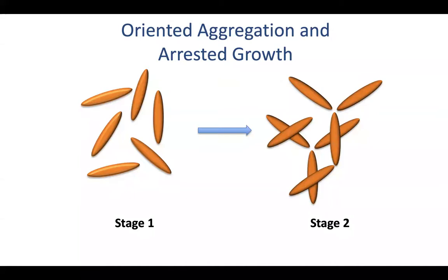And in fact, material scientists have synthesized hematite, and they found that when phosphorus concentrations are high, they poison certain surface sites. And so instead of growing as flat hexagonal platelets, which is how hematite normally likes to grow, it will instead adopt the spindle structure. Now, the next stage is that these spindles attach to each other. And this process was popularized in the late 1990s by Penn and Jillian Banfield, who described it as oriented aggregation. And the idea here is that hematite has a threefold symmetry.